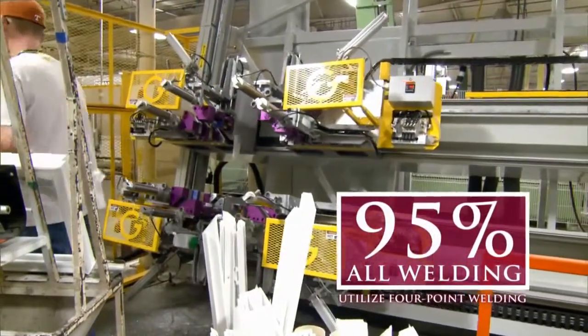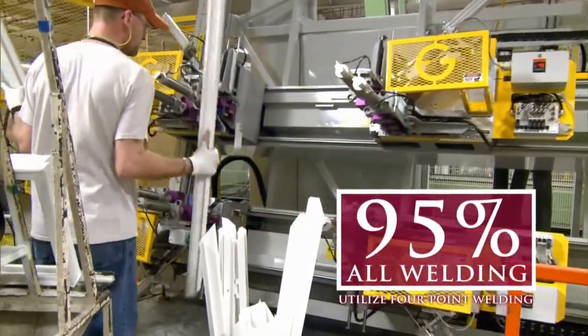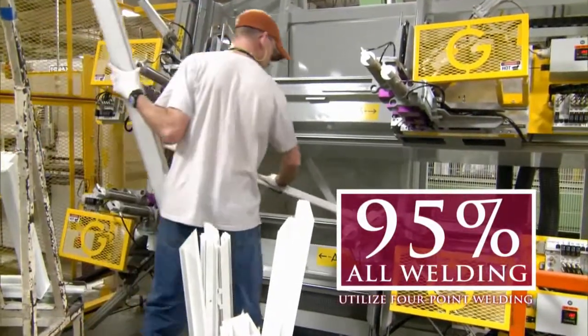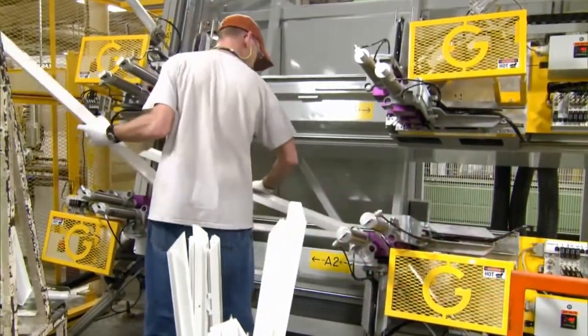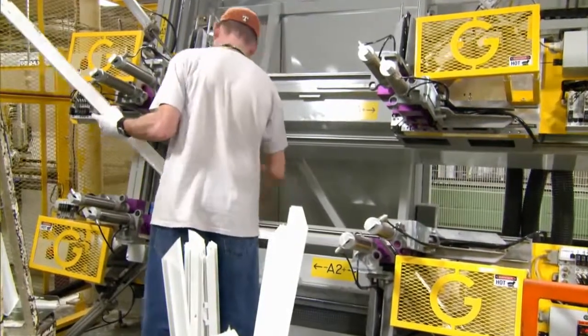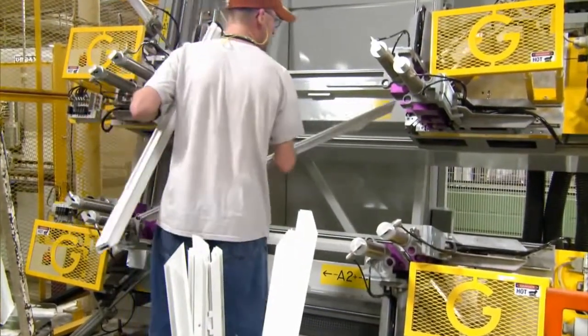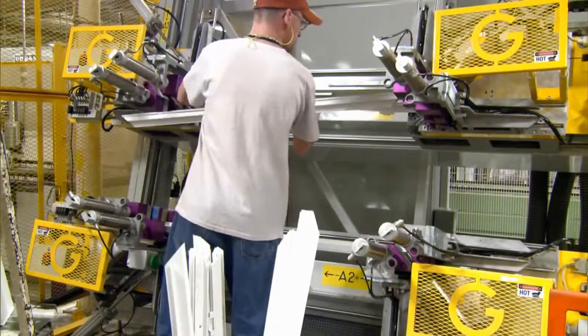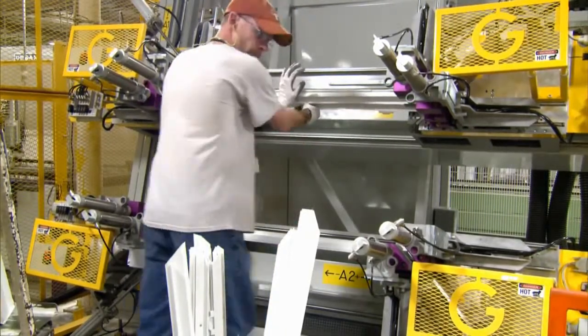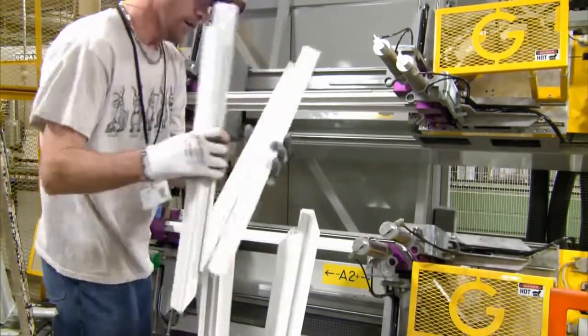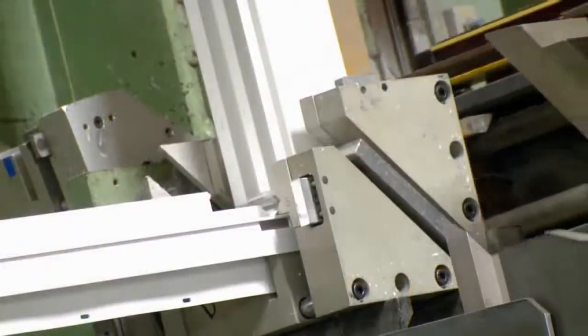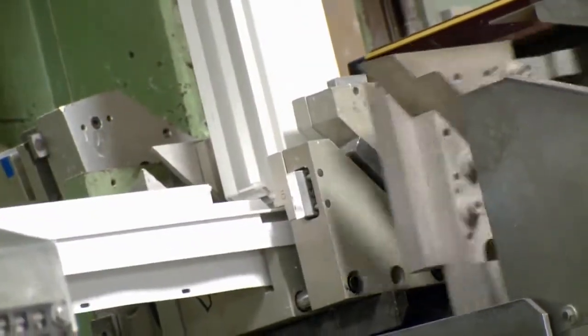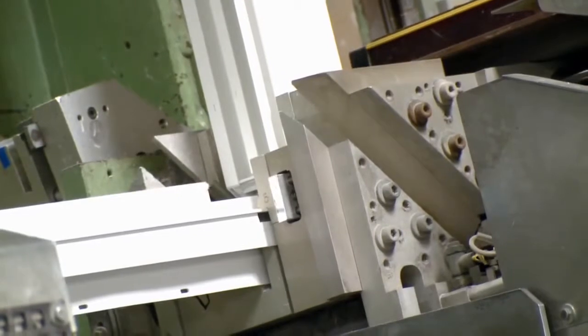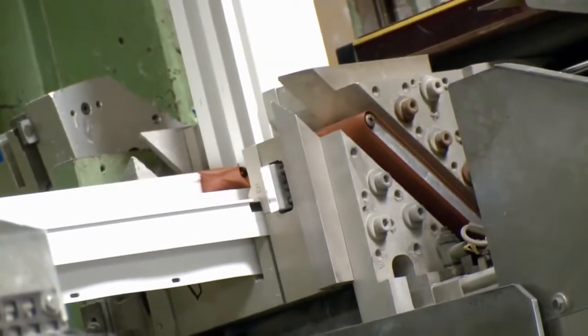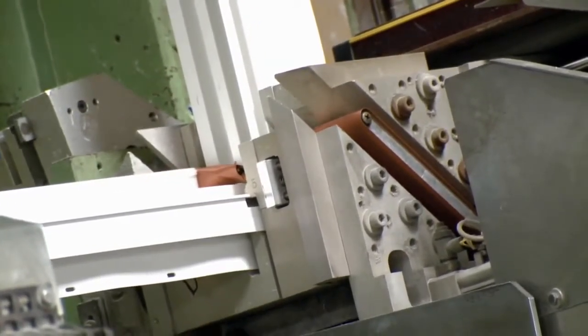95% of the welding we do is done on these special 4-point welders. Welding all 4 corners of the units at the same time ensures that we create it perfectly square. These special welders will also weld more than one sash at a time, ensuring a square, matched set for those particular units. The jigs on these fusion welders match our profiles precisely to make sure there is no twisting or warping at the miter and that each profile aligns perfectly.